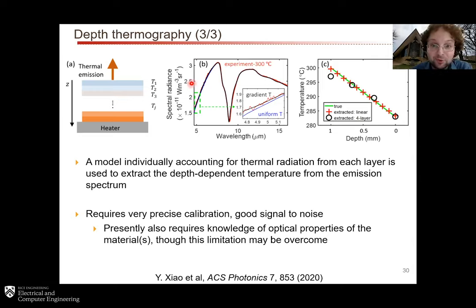So here is the spectral radiance that's measured, now normalized to a reference as a function of wavelength. And the experiment is done at a temperature of 300 degrees. And so you can see the experiment over here is a perfect match to two different theories. But if you zoom in all the way over here on the left, below about 6 microns, or maybe below about 5.5 microns, you see that the experiment, which is this red curve over here, is dead on one of our theoretical calculations, but deviates slightly from another one of our theoretical calculations.